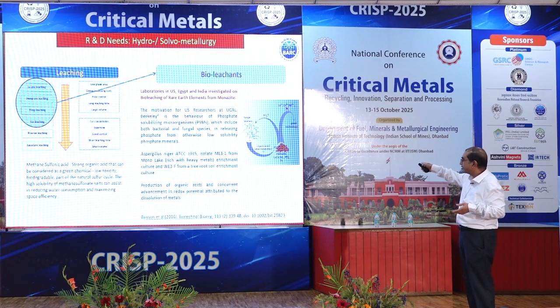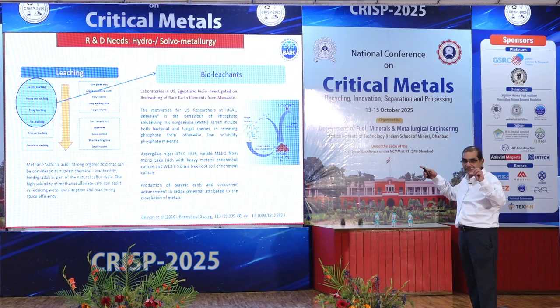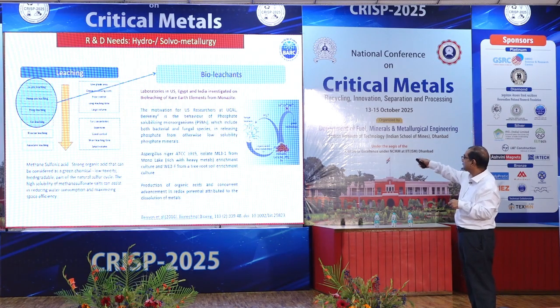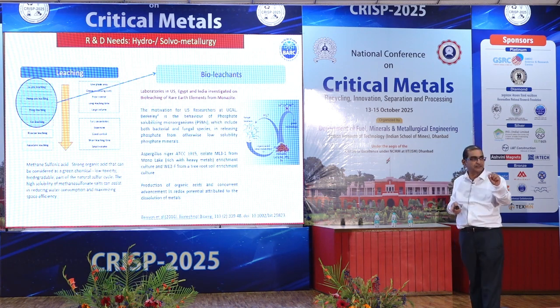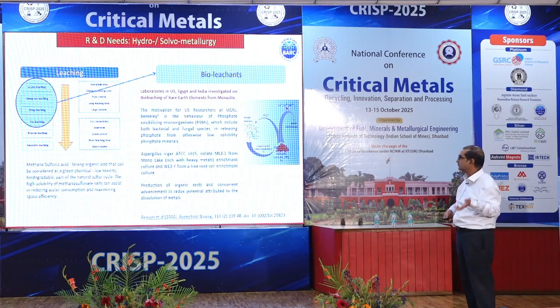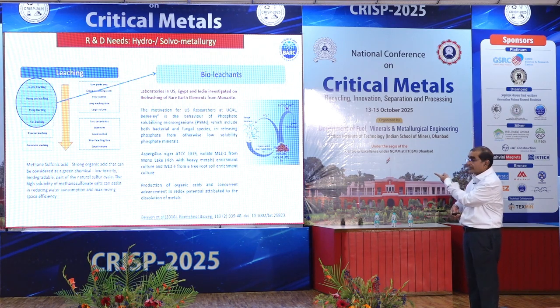If plants can break refractory minerals like apatite to take the phosphorus out of it, why not we synthesize a biomolecule which will be able to break monazite? And they were successful in that. Though the recoveries were 35 to 40%, still they could do it. They had to optimize the process. In India also we did it. And we have got a green strong organic acid called methane sulfonic acid. We have to replace the conventional mineral acids with this type of organic acids.